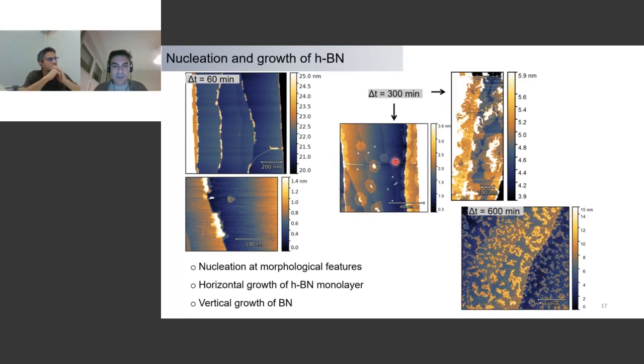And sometimes you see islands that are purely monolayer, whereas most of the time you already have a kind of vertical growth taking place in the middle. You see another area here where you already have some islands that are merging with each other, while we have this vertical growth going on. Anyway, if we grow then for 600 minutes, then we see the whole surface is covered with this additional vertical growth going on. So it's far from ideal.